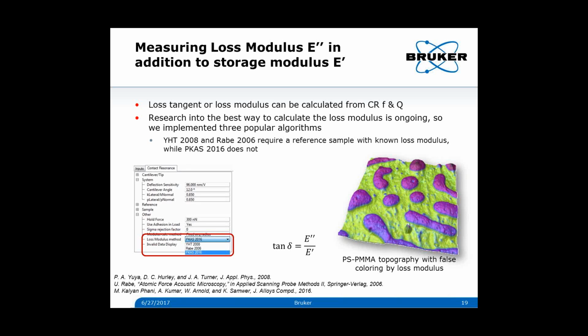The research into the best way to do the calculation is ongoing. So we implemented 3 popular algorithms. The references are at the bottom of the page. You can calculate both storage modulus, loss modulus, and loss tangent from these. Here on the right, we have a map of polystyrene PMMA topography, and we did a false coloring with loss modulus on there.